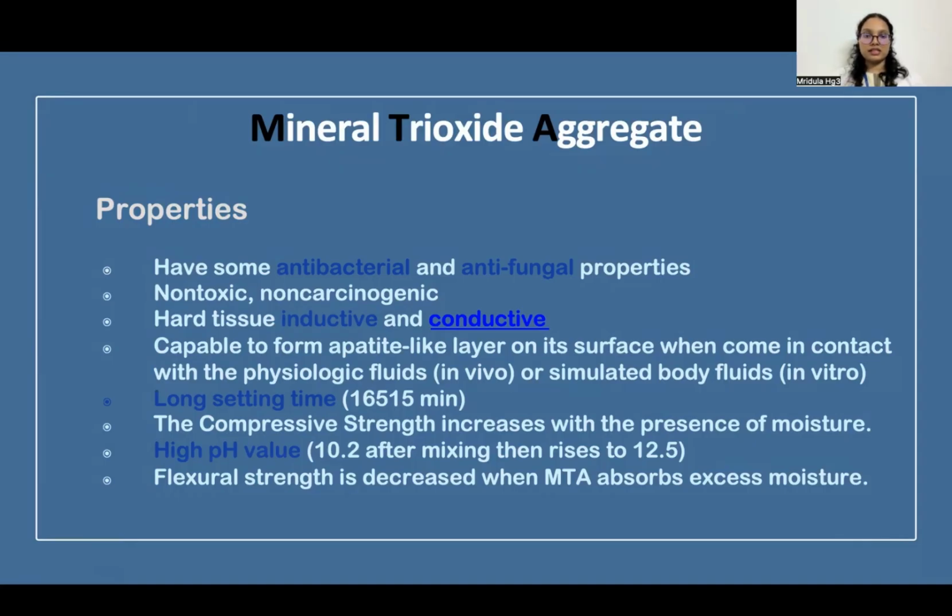They have a long setting time and their compressive strength increases with the presence of moisture. They have a high pH value, which can rise up to 12.5, and they have a good flexural strength. But when it absorbs excess moisture, the flexural strength decreases.